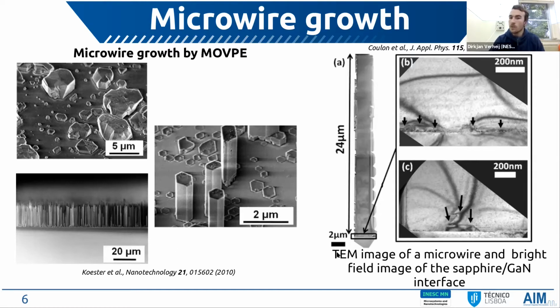And if we then look at the TEM image of a single microwire, which is shown here, contrary to what we observed in the previous slide, we do not see any black lines along the vertical axis of the microwire. And this means that the microwire is essentially dislocation free.